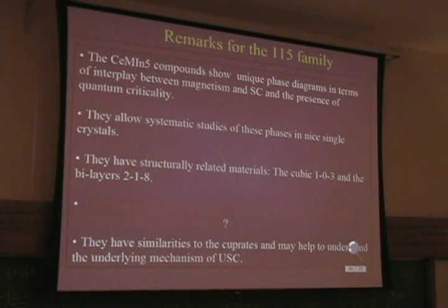There is one important question that we need to answer in order to understand heavy-fermion superconductivity in these materials, and they can help. The 115 and the related materials: why are there so many heavy-fermion superconductors in the same magnetic structure? You have a tetragonal compound, you have CeCoIn5, the 218s, the 122, CeCu2Si2, all of the family. All of them are tetragonal compounds. If you take the cerium compounds, all of them are in tetragonal symmetry.